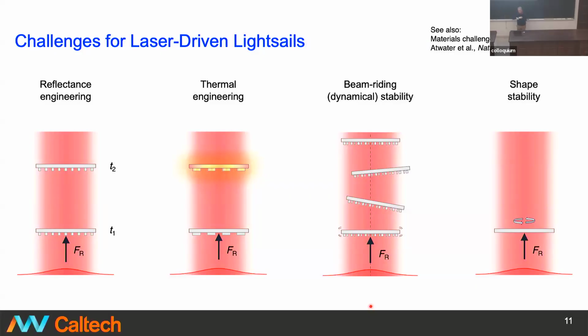And then, of course, because we have something that's 10 square meters in size and weighs 1 gram, that means the nominal thickness of this structure has to be something like a few hundred nanometers. And that means we have a membrane. We don't have a rigid body. If I have something that's a few microns in size and a few hundred nanometers thick, it's rigid. But by the time it gets to be tens of microns to 1 millimeter in size, then it becomes flexible. And so you have to think about the shape stability as well.